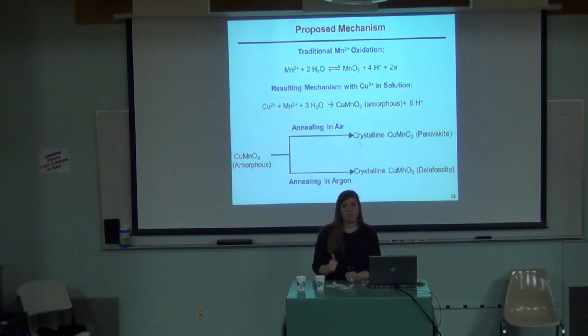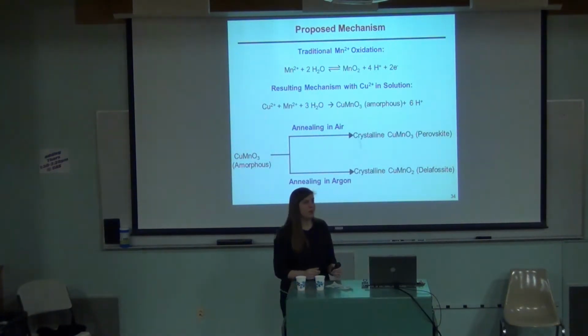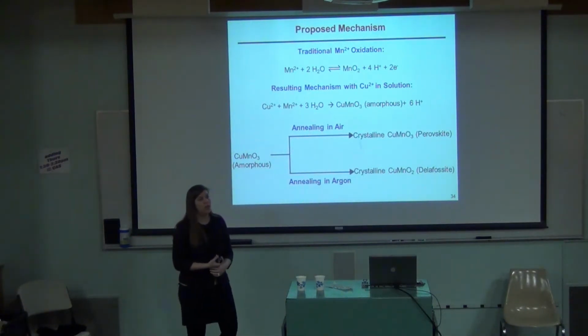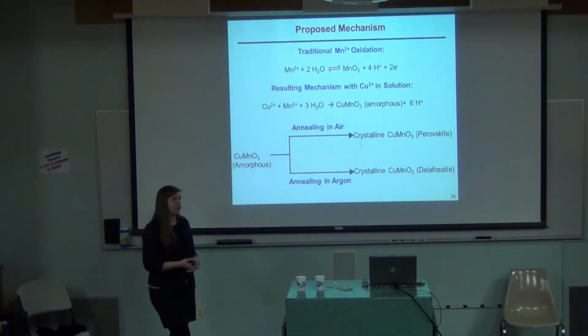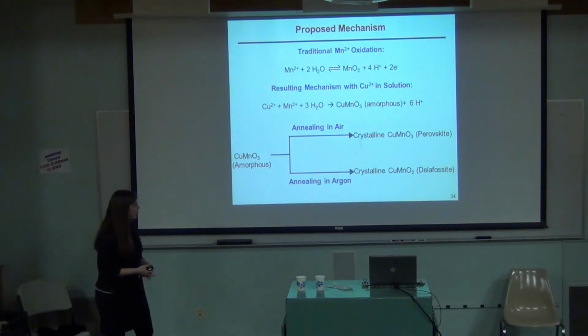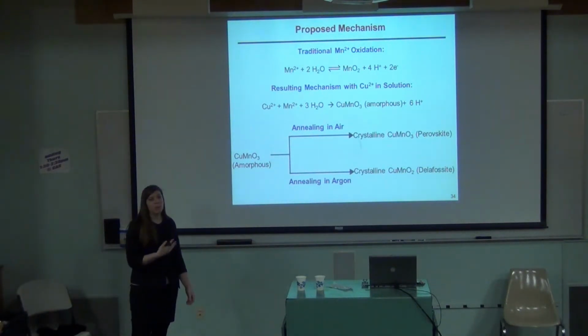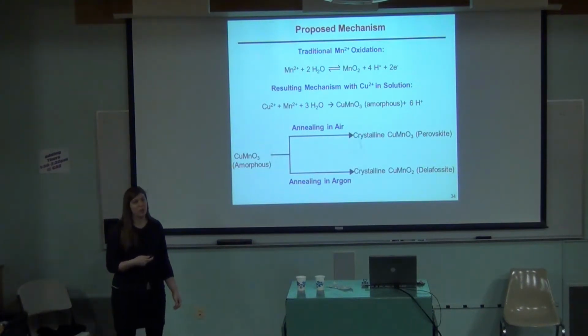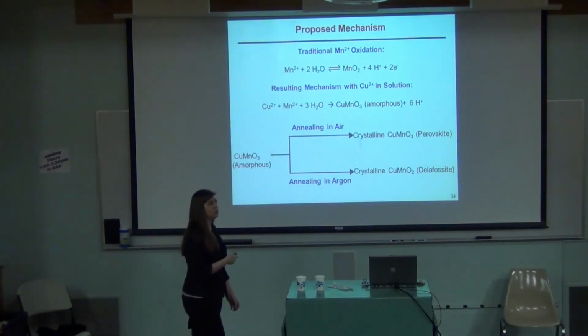And I picked manganese because I knew manganese very easily went to lots of different oxidation states, so I thought if I had to pick something, this would be my best bet. It also was the most soluble at lots of different oxidation states, so I thought I had the best shot with that. And I did in fact get a film. The problem is that I actually was able to produce the manganese very easily, but the copper didn't want to be reduced at the same time. So it decided it was going to stay as 2+ while the manganese went to the 3+.